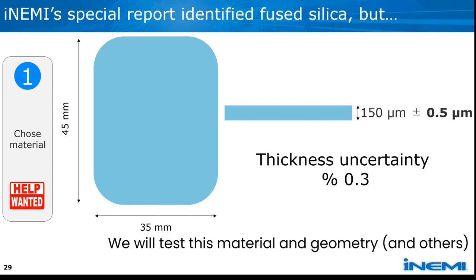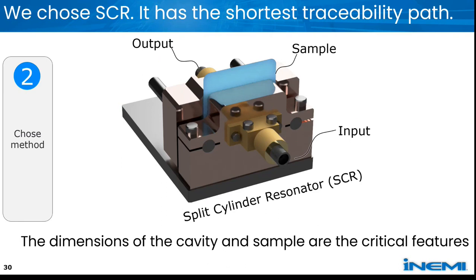That total thickness uncertainty might sound unbelievably small. You might think, wow, that seems like a really, really low total thickness variation. Isn't that overkill? And the answer is no. We actually need that level of uncertainty on the total thickness variation in order to hit that specification that iNEMI talked about, which was that 0.2% uncertainty on dielectric constant and loss tangent. So in order to deliver that type of uncertainty to you, we need to do much, much better, and that's what's required. Would you like to pipe in, Ermi? Okay. Okay, so the next step is to choose a method.